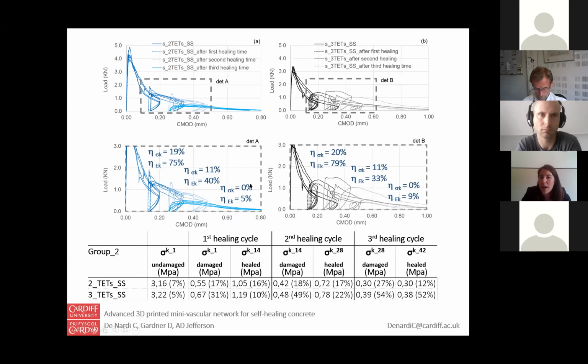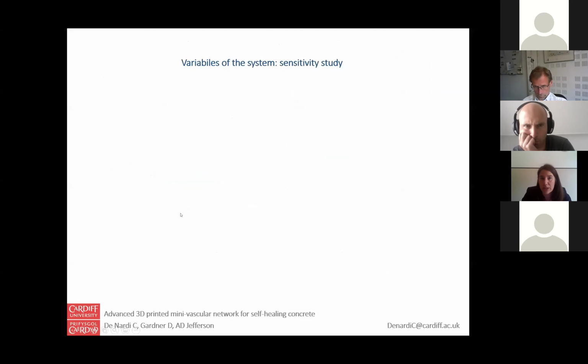Well, when we damage and heal again, so after the third damage healing cycle, it appears that the concrete TET system has consumed all the healing agents stored inside the TETs. So the recovery is almost negligible. However, we can see a positive trend in terms of stiffness.